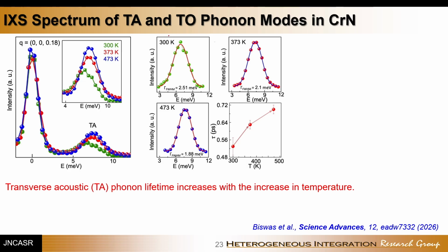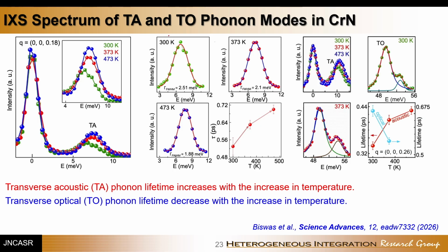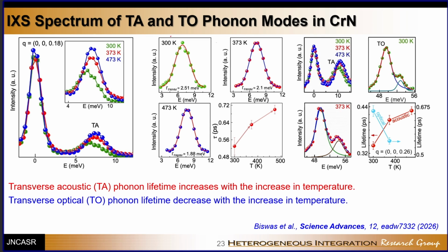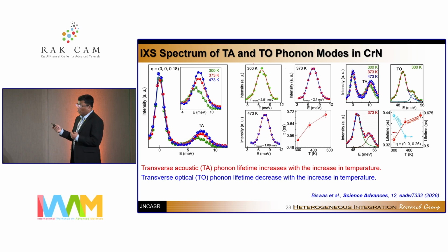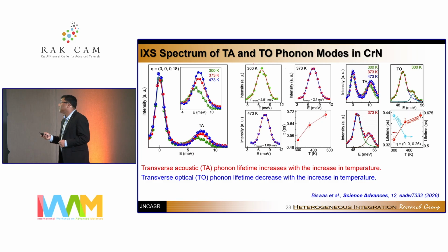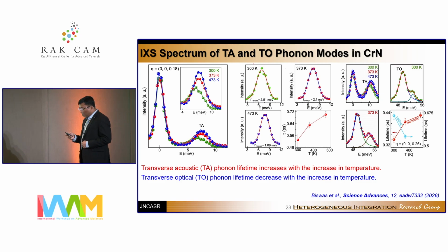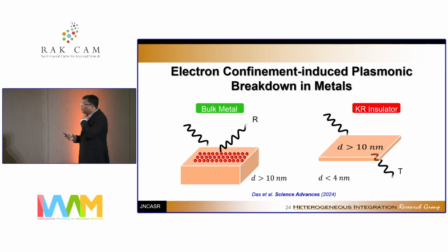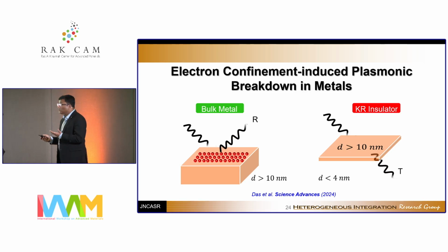And since thermal conductivity is proportional to the acoustic phonon lifetime, because the phonon lifetime increases, thermal conductivity also increases. This is for the acoustic phonons, but optical phonons are not impacted by spin-phonon coupling, so the optical phonon lifetime actually reduces, just like in normal materials. So this is the work on chromium nitride, where magnetic stress basically drives a structural transition, and the structural transition leads to an electrical transition, and the consequences are felt in transport measurements.